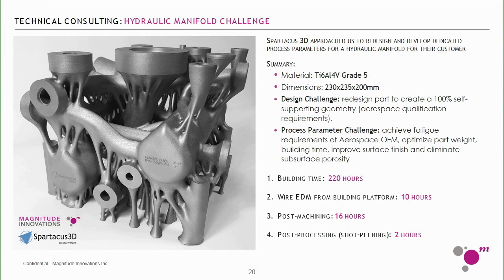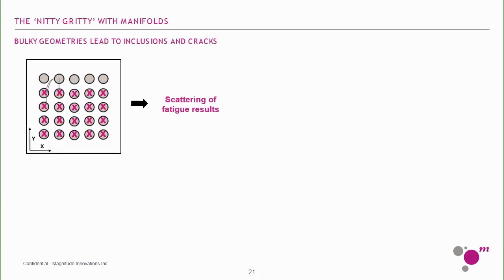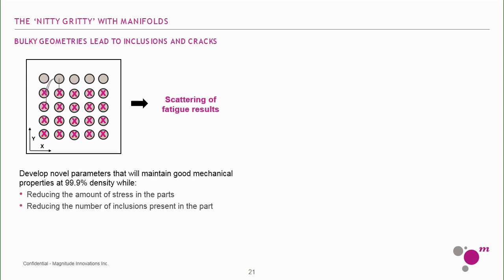So the first thing that we did is we took a look at the impact of this massive geometry on the mechanical properties. When you have a lot of area that's being exposed per layer, the statistical defects actually increase in the process. And that has a direct impact on your fatigue, but of course you're not going to be testing that every time you run a build, because that means that every iteration is going to take about 4 months. So what we did is we first tried to understand the scattering of these results in a way that doesn't require us to build the whole manifold, and reduce the residual stress in the application, and then also reduce the number of inclusions in the parts.